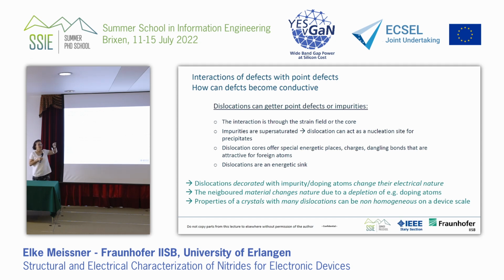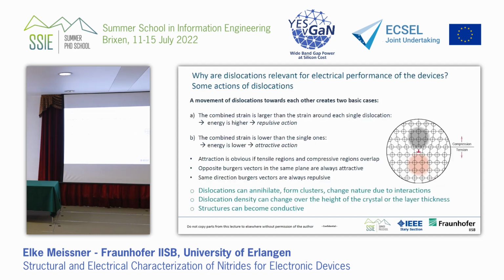And now imagine you put dislocations in this perfect arrangement with an evenly distributed carbon. You have learned that a dislocation has a strain field which stores energy. So what happens? The dislocation can gather the point defects or the impurities. They grab this extra carbon and gather it around it. So inside the strain field, you can gather the impurities. Imagine you distribute a dopant or an impurity over the whole lattice. Then these start migrating to the strain field around the dislocation.